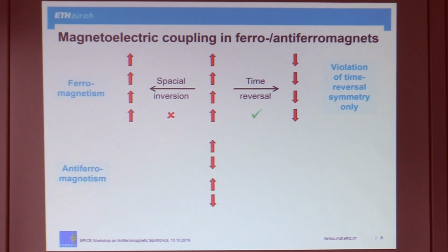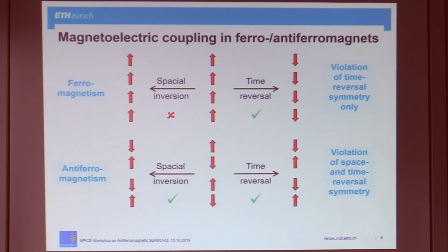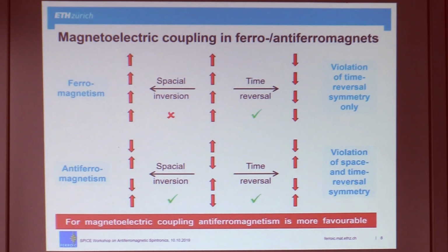And that's very different for antiferromagnets. Here, if you apply spatial inversion and time reversal symmetry, they are both broken. They are both not symmetry operations. So antiferromagnets, therefore, are the candidates that suggest themselves if you want to talk about magnetoelectric coupling phenomena, not ferromagnets. This is also why many of the multiferroics, those compounds with simultaneous magnetic and electric order, unite ferroelectricity and antiferromagnetism rather than ferromagnetism, because it's the better basis for having magnetoelectric coupling effects of any sort.